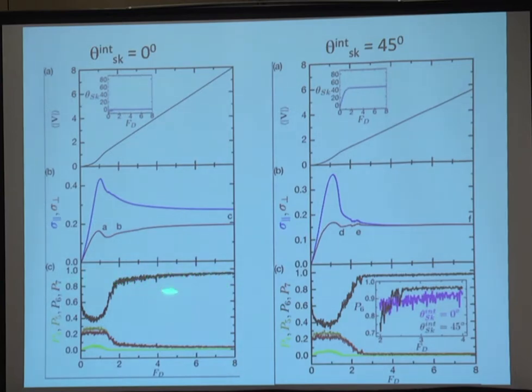So if you have a completely triangular lattice, your black curve measures the fraction of six-fold coordinated skyrmions, which will be close to 1. In this case, this is the overdamped case. So what happens is you start off in a pinned state, it depins plastically, so you have a large amount of defects, and then at high drive, it gradually goes to the ordered phase, or dynamically ordered. But your fluctuations are always strongly anisotropic. You have much stronger fluctuations in your direction of drive than your perpendicular.